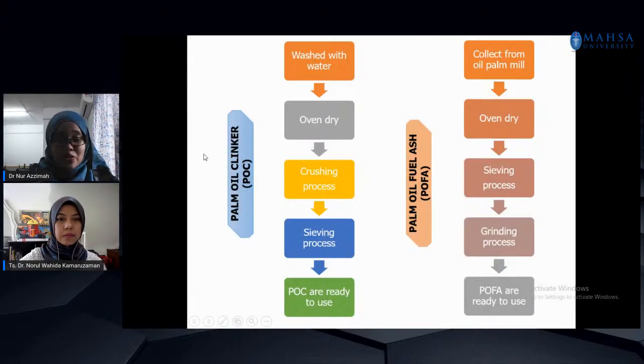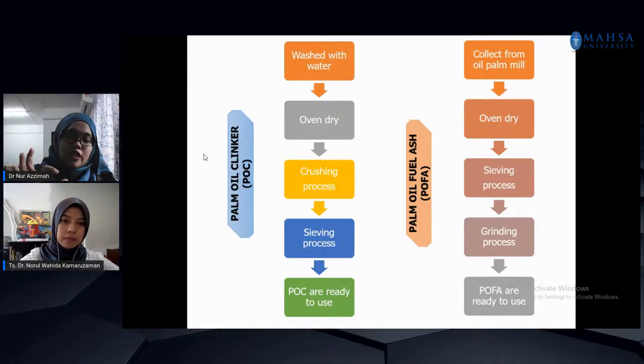And the same thing, you have to process the palm oil clinker. We cannot simply replace it, because it is actually big, in big chunks of rock. When you take the sample, you have to wash it first, because there will be some fiber around the clinker, and this fiber will absorb a lot of water if you mix it together. So you have to clean it first. After you wash, you have to oven dry until SSD. After that, you have to crush this palm oil clinker so that it becomes smaller particles.